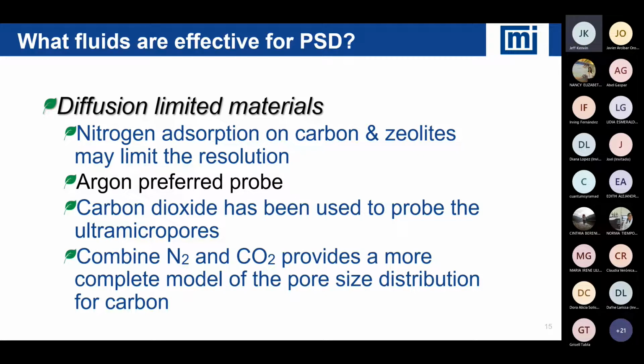CO2 has been used very effectively for microporous materials, but there are limitations there. CO2 doesn't necessarily have strong interactions with some chemistries. So CO2 can be very effective for carbon. It may not be quite so effective for non-alkaline exchange zeolites, so typical zeolites that are used for catalysis. And likewise, some MOFs may not be particularly suitable for CO2 adsorption. So there are some surface energy limitations that we all need to be careful about.